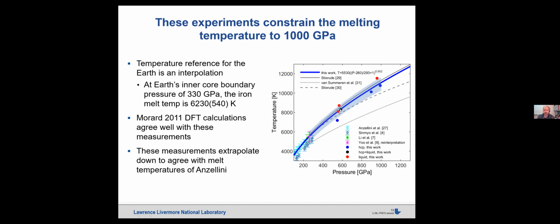Then if you look to higher pressures where there actually is no data, the highest pressure temperature measurements are by Sinmyo very recently in 2021. So this is sort of the first data in this regime, about 3 times higher pressure than previous measurements, and it actually agrees really well with the Morard 2011 DFT calculations, and it extrapolates well down to the Anzellini et al. melting curve measurements, where I would say these temperature measurements have an uncertainty of 500-600 degrees at low pressures and at high pressures 1000 degrees or so.